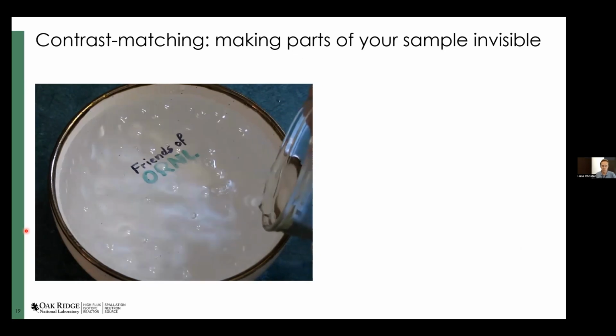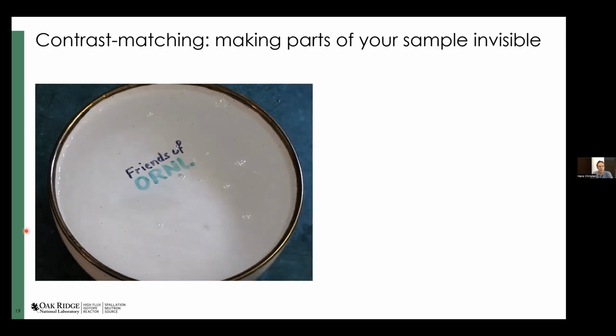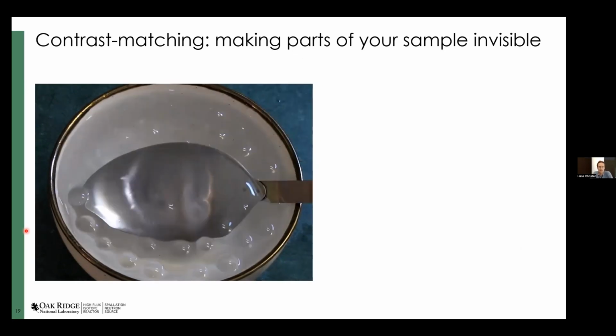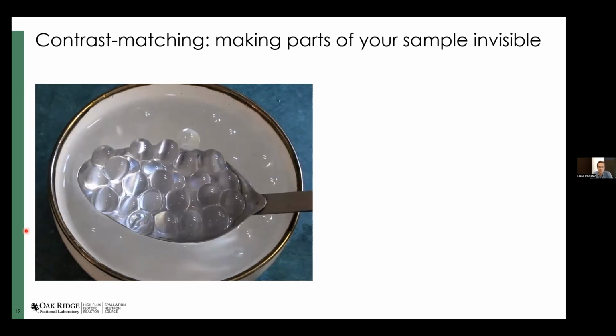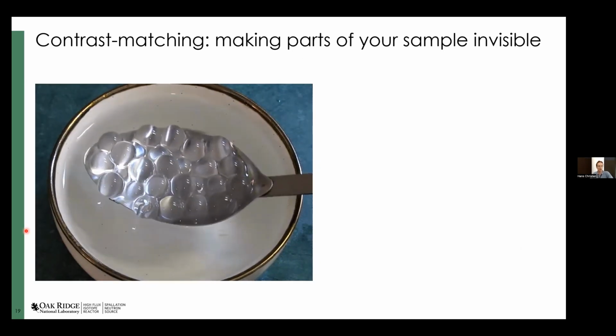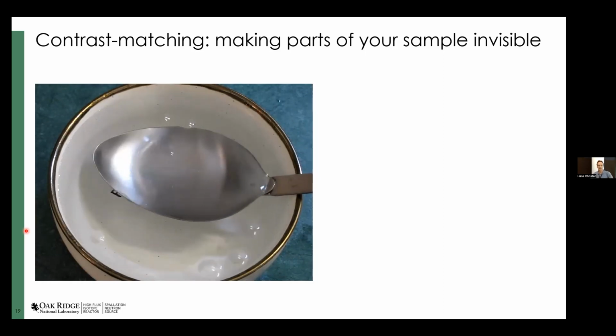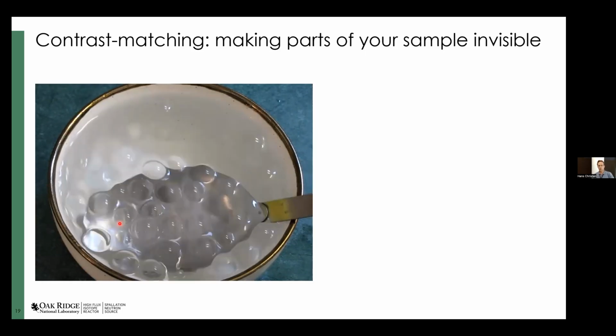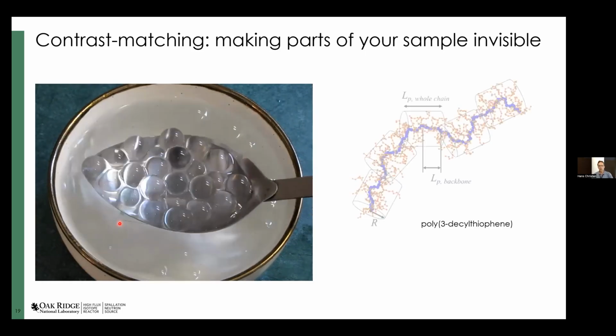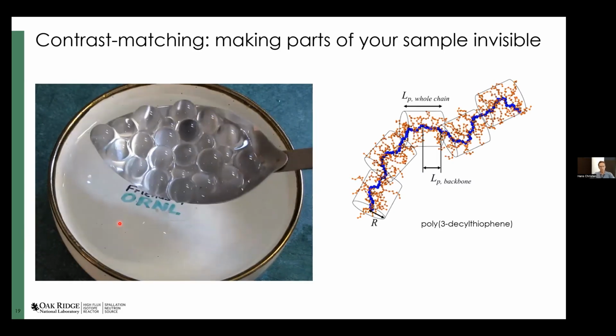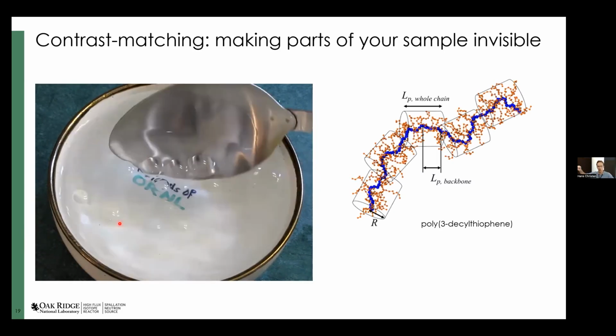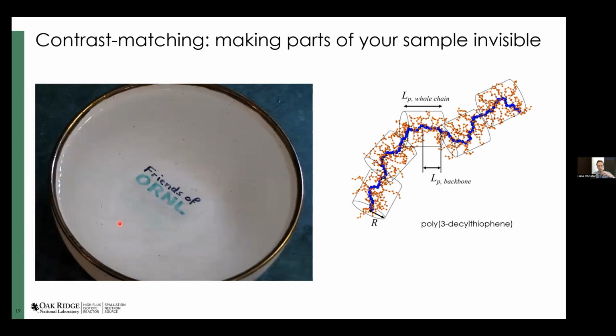This is not removing the beads. The beads are still there, but they're now surrounded by a medium that has the same optical properties as the bead, and therefore the beads essentially become invisible to the eye. Now, obviously, we're doing something quite different with neutron scattering, but imagine that you have a polymer, which is typically a backbone, a long chain of carbon atoms with complex arms around it, and you want to understand the shape of this backbone. The way to do this is to make the side chains invisible.